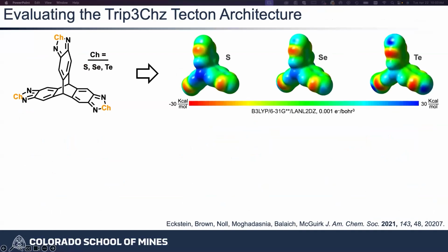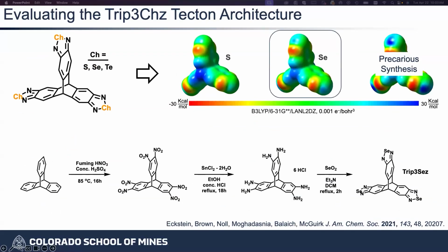we set out on this molecule here. I don't have time to really explain why, but we have this rigid triptycene core with these chalcogen diazolyl moieties on there. We could do ESP maps using DFT, and we can see that if we go from sulfur to selenium to tellurium, this blue spot is getting darker and darker. That again is our sigma hole. All right. So we wanted to work with tellurium.